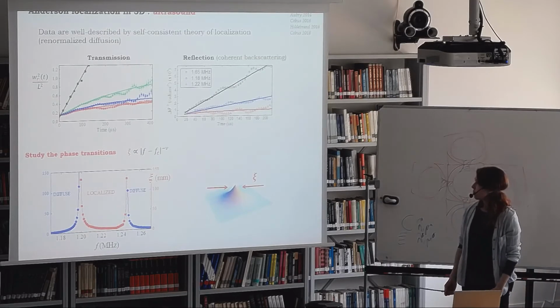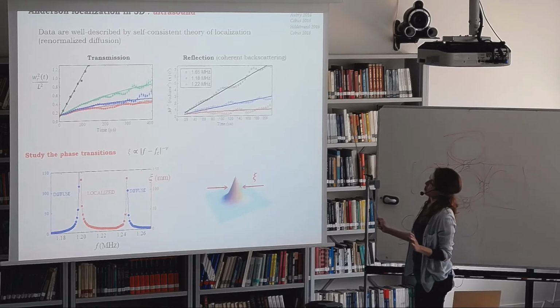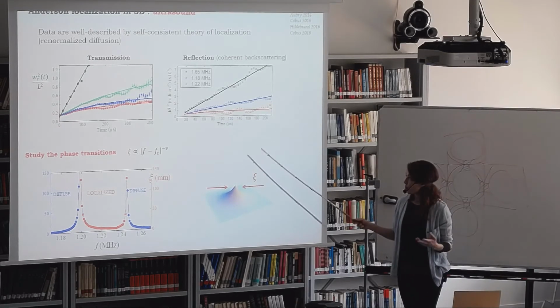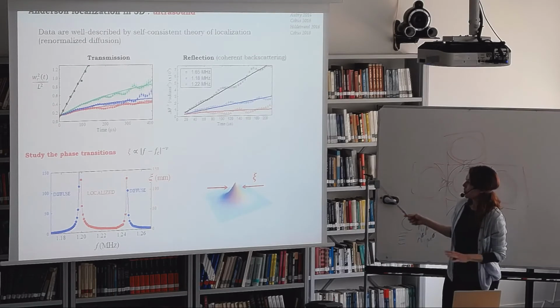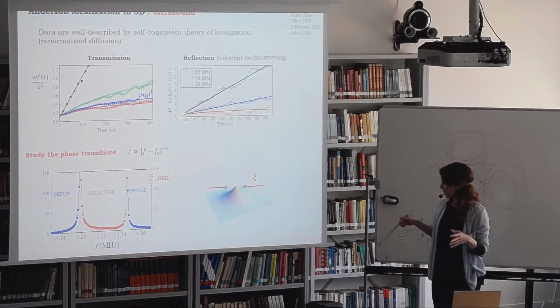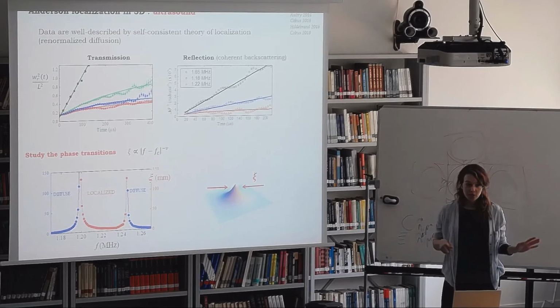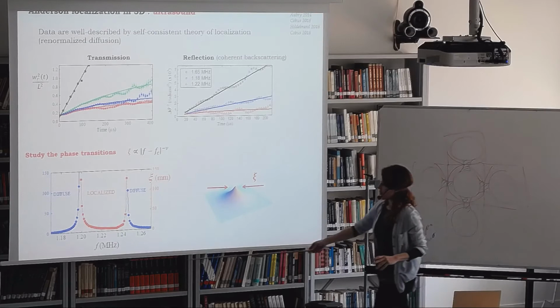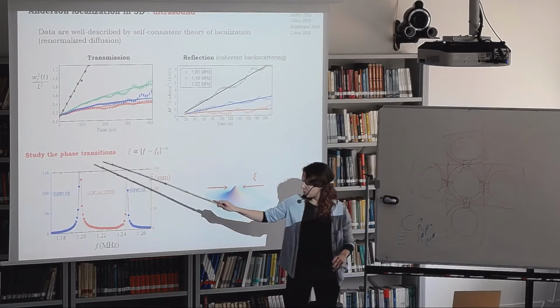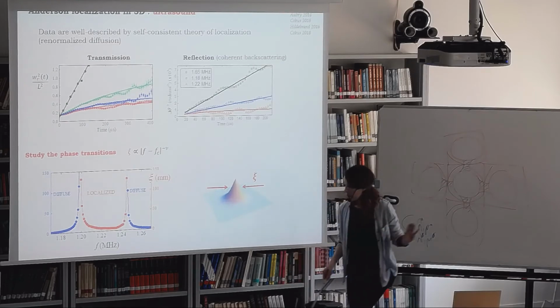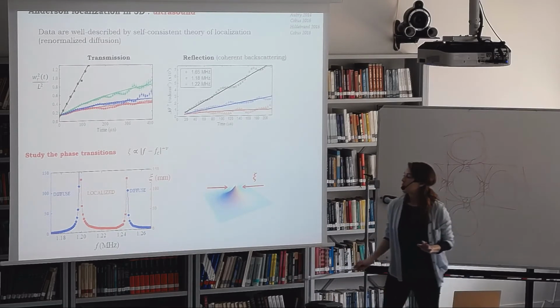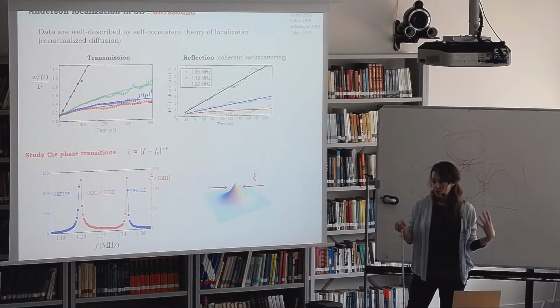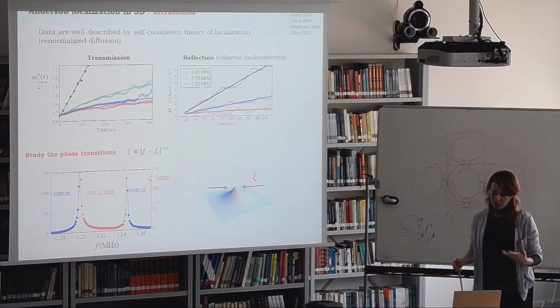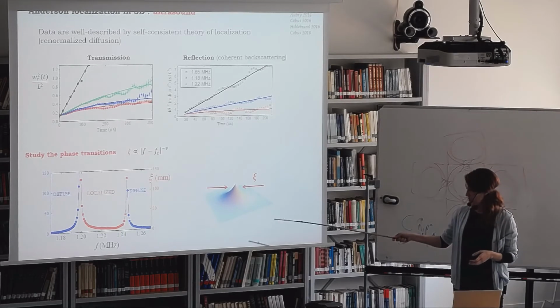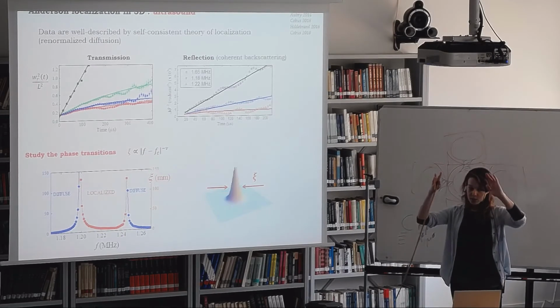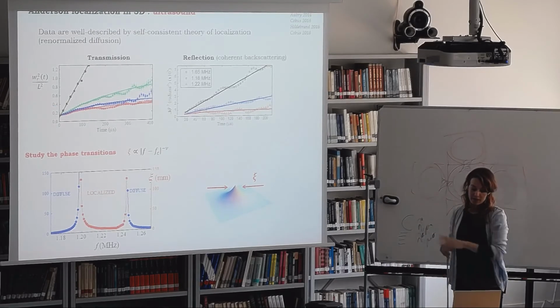We've shown that by comparing our data with the theory, the renormalized diffusion theory, we can describe the behavior very well. And in fact, this lets us measure the localization length, so the spatial extent of the waves, as a function of frequency. Okay, so we saw that at low frequencies, we have conventional behavior, which can be described by the diffusion approximation. But then as we increase frequency, we go into an actual phase transition into a localized regime where the waves find it much harder to escape the sample. We actually found 2 phase transitions. So this means that we saw an entire localization regime bounded by a diffusive regime on either side.